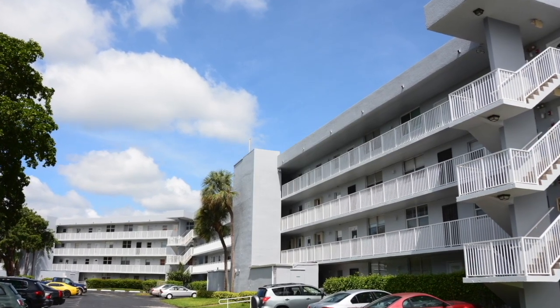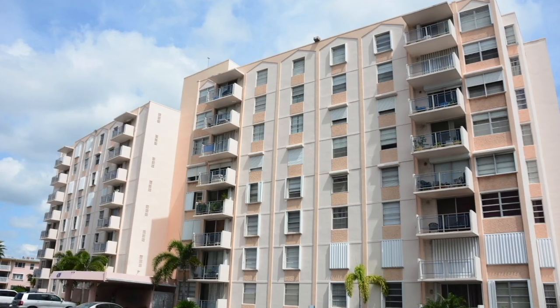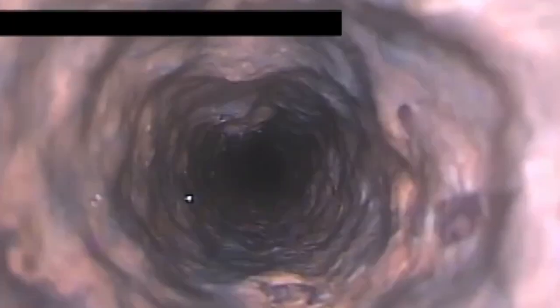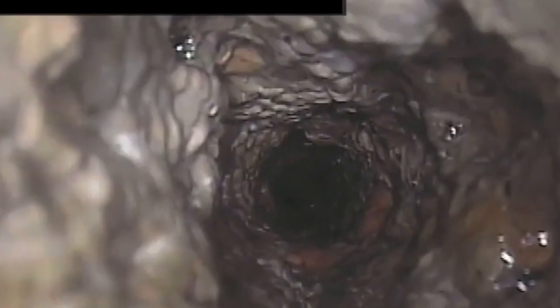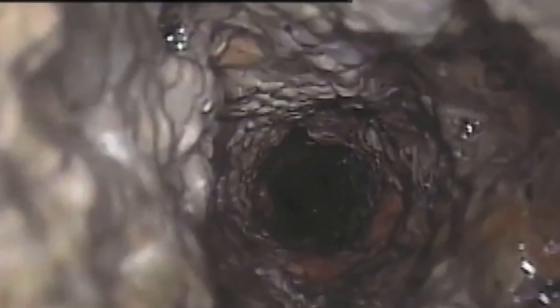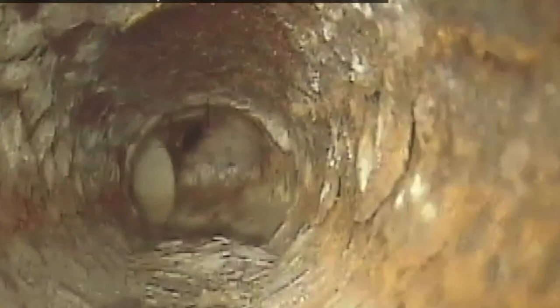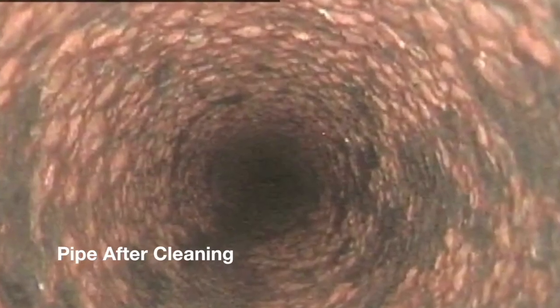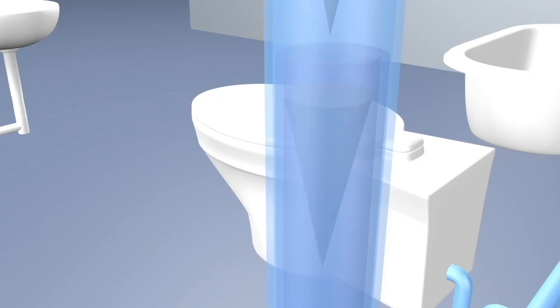Chances are your vertical stacks have been in service for 20 to 30 years, and during that time they have absorbed soap, grease, and organic waste that build up bacteria that eventually coat and pit your vertical pipes. That, along with the corrosion and scale that forms on the interior of the pipe, creates a challenging environment for a structural liner to perform properly, because no mechanical or hydrojet cleaning process will deliver a pipe that is completely free of scale, grease, soap, or organic buildup. The remaining buildup in the pipe should factor into which installation method you should choose, because gravity and flowing water will take their toll on the final product that is installed in your vertical pipe.